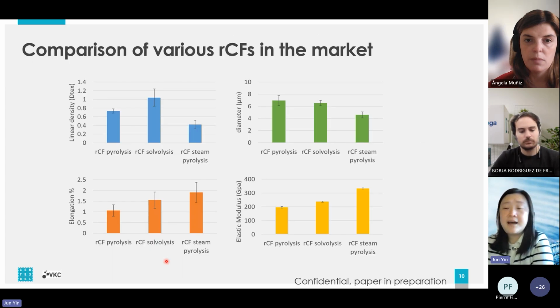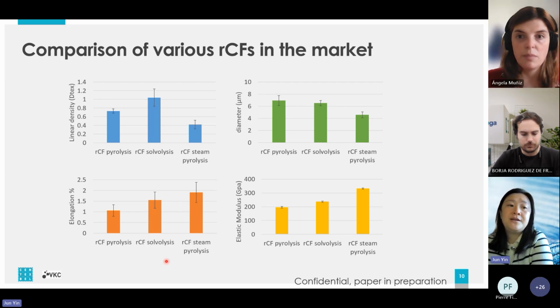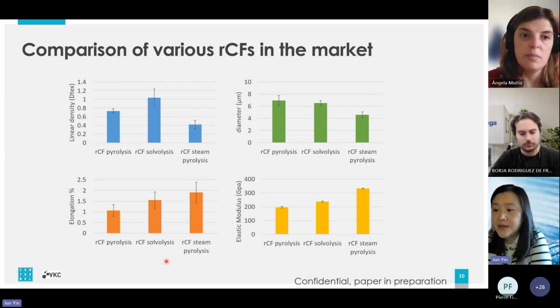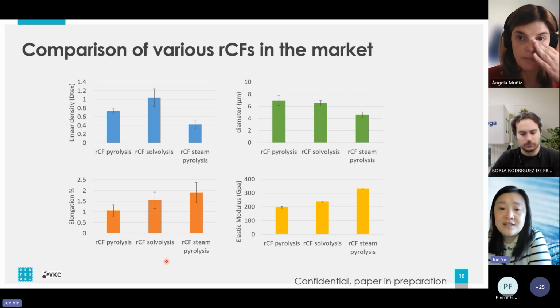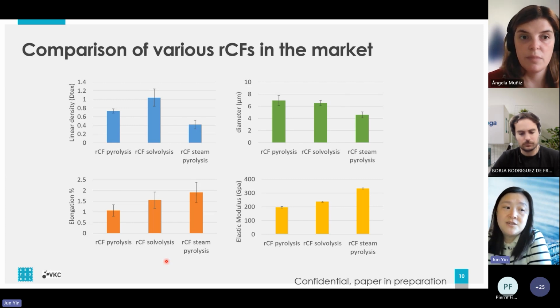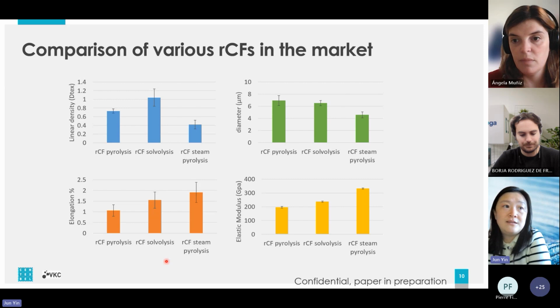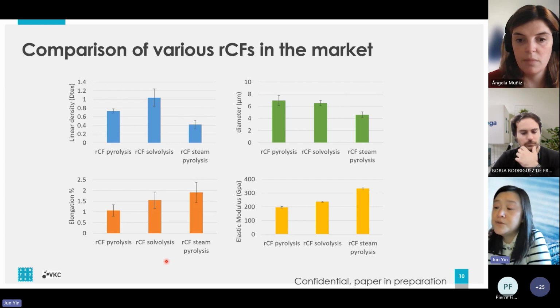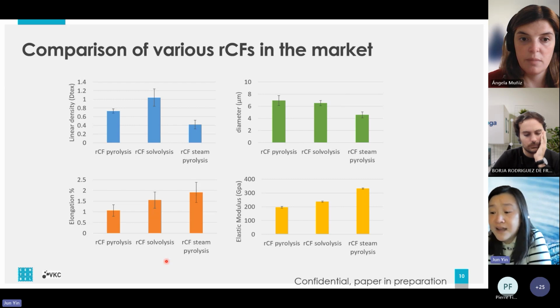So now, for the first time, we try to purchase different kinds of recycled carbon fibers in the market. Then we compare them in different properties like linear density, diameter, elongation, and elastic modulus. But the problem is the exact composition and original type of fiber can't be determined. So it's difficult to compare them. In order to ensure good reproducibility and comparability of the test, we decided to purchase the carbon fiber waste ourselves. Then we sent it to our industrial partners to do the pyrolysis to remove the original sizing and to simulate the recycling process of end-of-life composite.